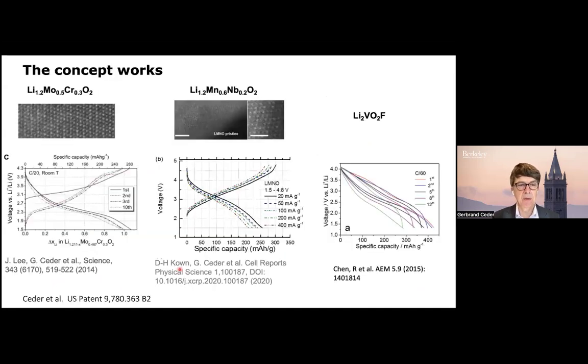And the concept works. It's been shown by several people, including ourselves, in different materials. This is between 5 and 10 years old. There's our work in Science on the molychromium system. Here's STEM data of a fully disordered material, and you see that this really cycles almost a full lithium per formula unit. Here's a manganese niobium one that we did with some people in Japan. And then there was the early work in Europe by Chen and Fichtner on vanadium oxyfluorides, which were disordered and also cycled, though with low rate capability.